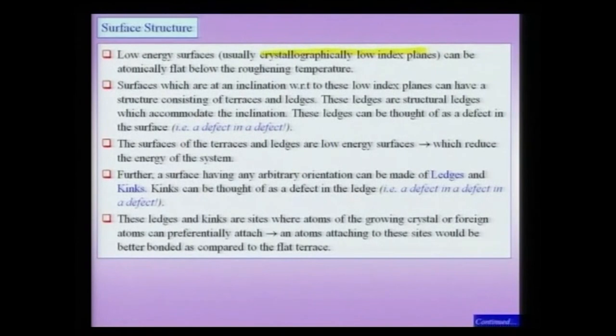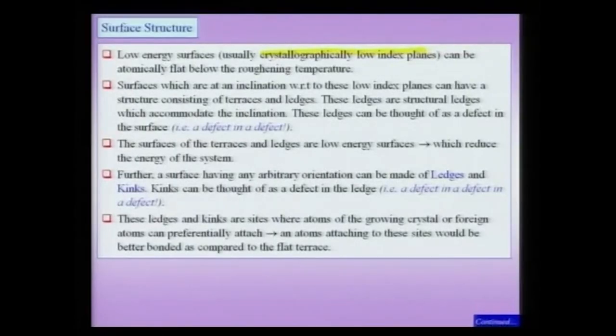What is the structure of a surface? If I have a crystal and anneal it for long times, the crystal will want to put up low-energy surfaces to minimize cost to the system. These low-energy planes typically are the crystallographic low-index planes. The crystal puts out these low-energy planes — they can be atomically smooth below the roughening temperature. The roughening temperature is the temperature above which the surface becomes very rough and it is no longer valid to talk about flat atomic planes. Below this temperature I can talk about crystallographic low-index planes which are low-energy and atomically smooth.